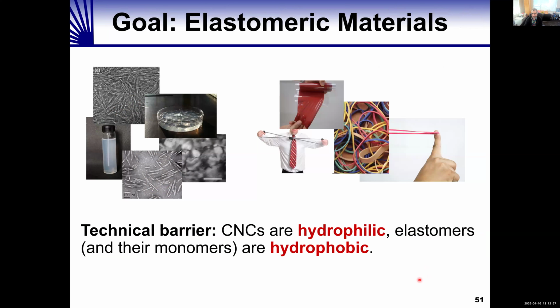Another goal that we've had for a long time is to make elastomeric materials with this structural color from cellulose nanocrystals. But for a long time, we couldn't overcome a technical barrier, which is that cellulose nanocrystals are hydrophilic. They love water. But elastomers, like the materials in rubber bands and other plastics, and their monomers are all hydrophobic. They phase separate out of water. So we spent many years trying to make elastomers with cellulose nanocrystals, but failed miserably in our lab.